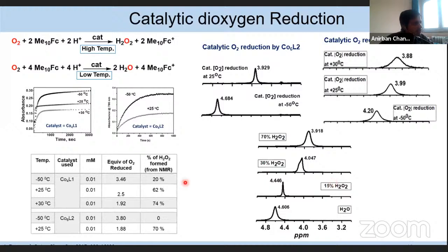So from here, I conclude that around 20% of hydrogen peroxide forms for the tetranuclear cobalt complex at minus 50 degrees centigrade. Whereas if I increase the temperature and I did the catalysis at 30 degrees centigrade and measured the NMR, I found the signal is shifted to 3.8 ppm. And for the 70% authentic hydrogen peroxide at the reaction conditions, the signal comes at 3.9 ppm. And so I conclude that more than 70% of hydrogen peroxide, around 74%, is formed here.